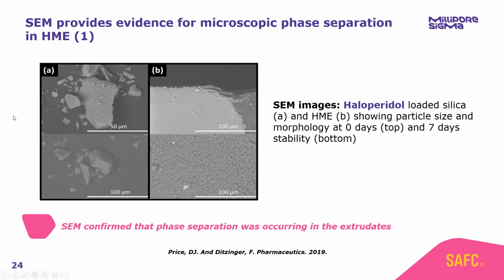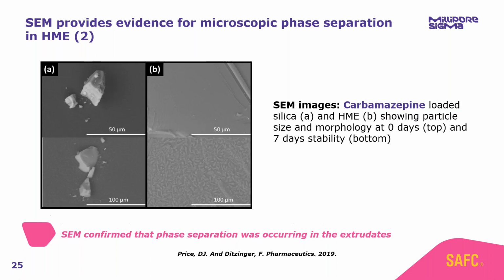Here we have haloperidol. Haloperidol-loaded silica is on the left and haloperidol HME is on the right. Our fresh sample is on the top and our 1 week sample is on the bottom. No change in the silica was expected, no change was observed. However, for the extrudate, we've gone from a relatively nice homogeneous surface to a surface that looks totally different. It looks heterogeneous. We have these kind of globule-like structures on the surface. This really confirms that we have phase separation in our extrudates.